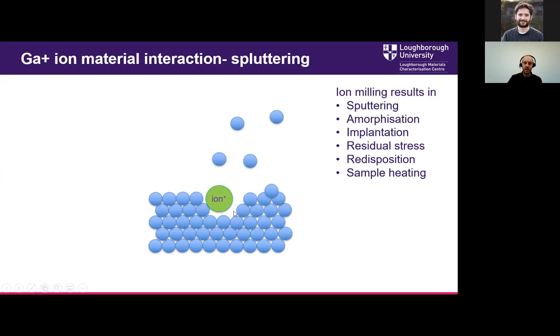So the ions hit the surface, they sputter some material away, and some material will be redeposited on the surface. We can also have some ions that remain inside the surface, so they're implanted, and this can result in residual stress. The action of hitting the surface with the ions also causes sample heating. Along with this, we also get emitted electrons, so we can start to form images.